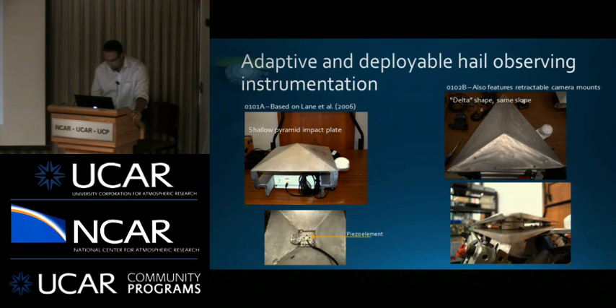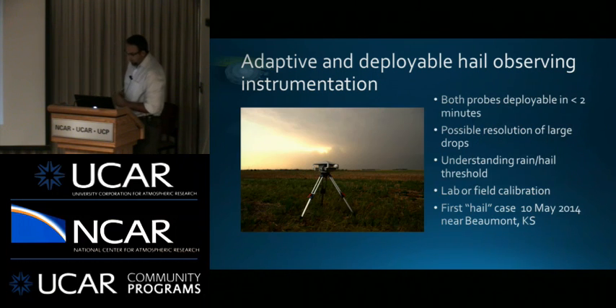So there's one of the first deployments of one of the probes, and you definitely can do it in less than 2 minutes. And I'll show a little bit of data. As a raindrop or hailstone impacts the device, you get that nice impact signal, and you can sample fast enough to actually extract some information. Now, you could get simultaneous impacts, and you just sacrifice some of those things, knowing that you wouldn't be able to extract that.